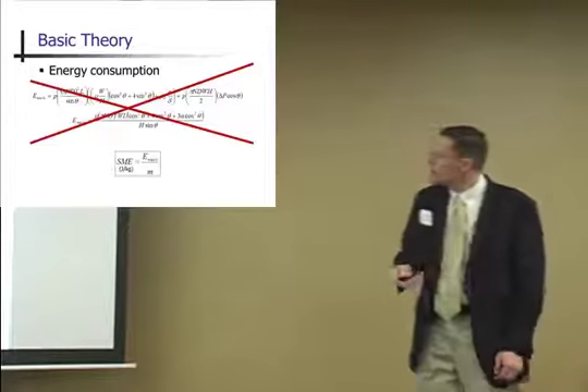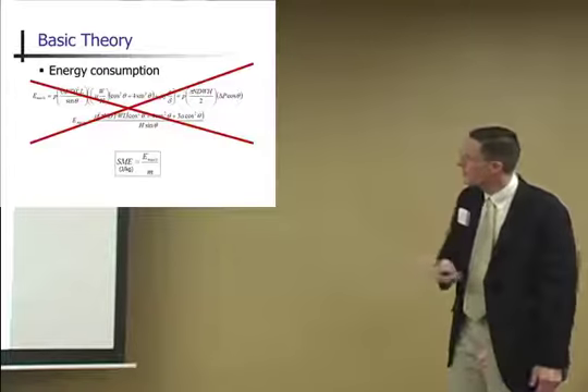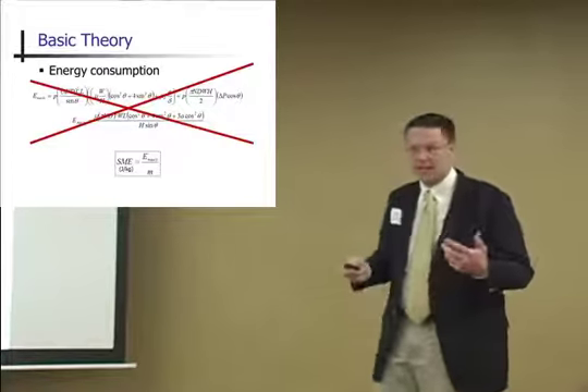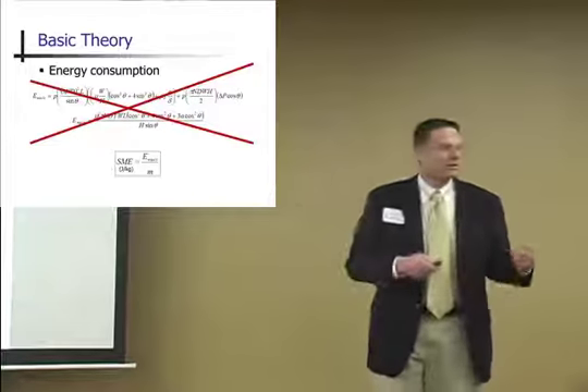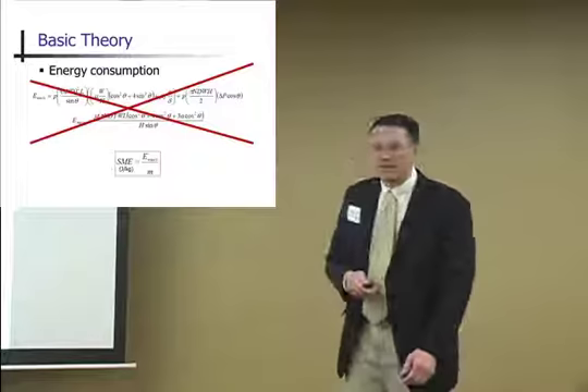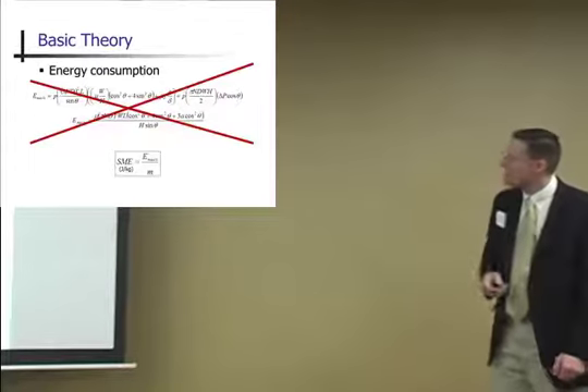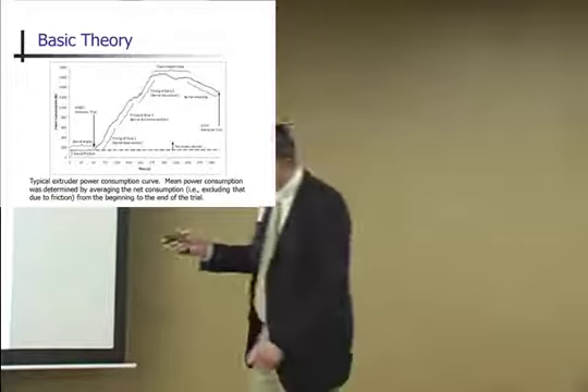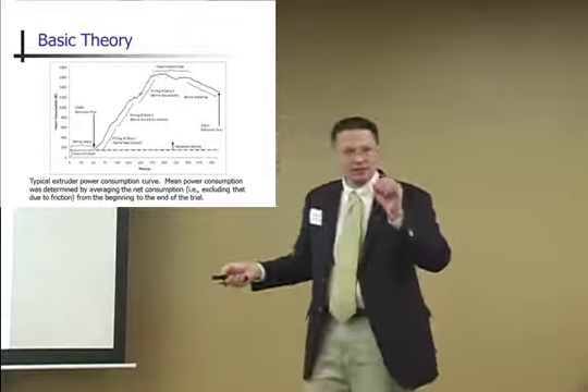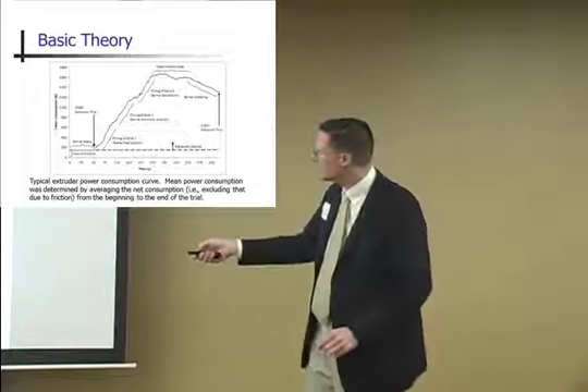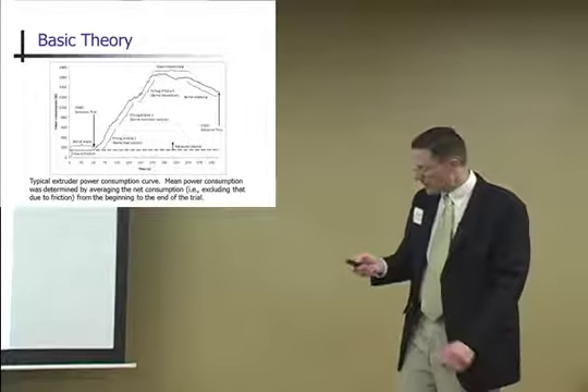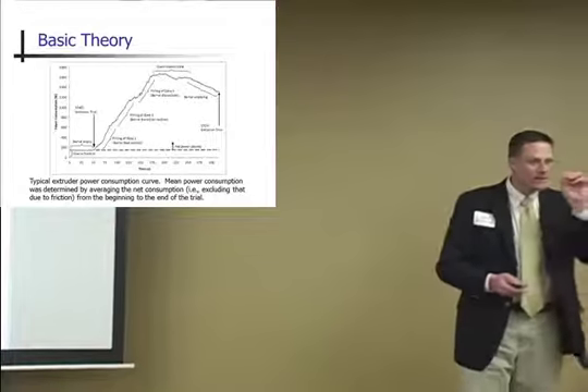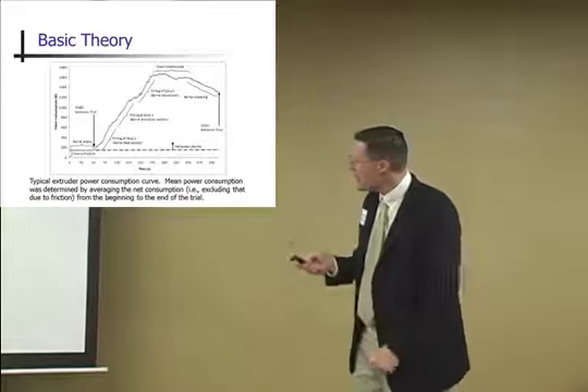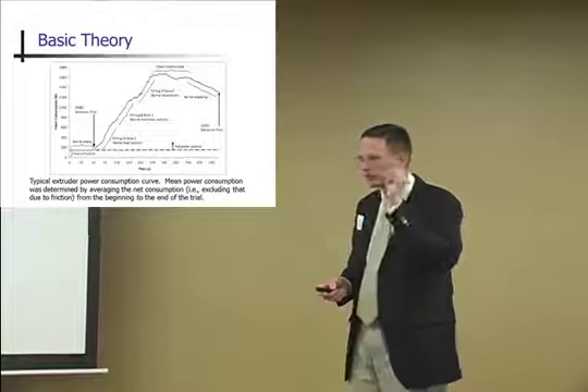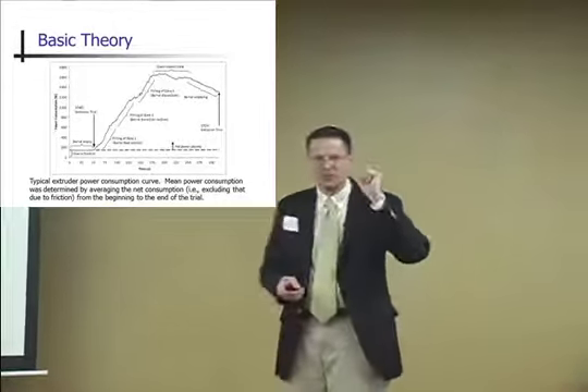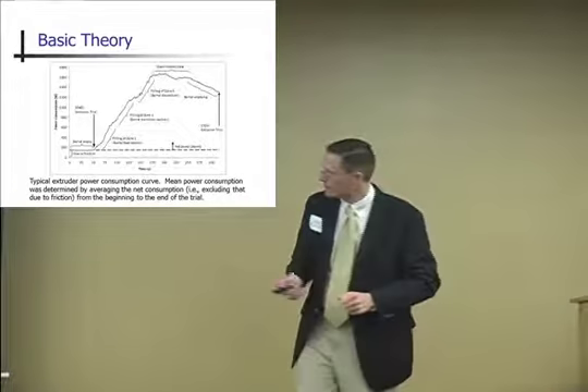So if we want to quantify energy consumption, this is how you quantify energy consumption. It depends on your geometry, your speed, your temperature, your material characteristics. You know what? I don't want to do that. You theoretically can measure the heat that you add, the electricity that's added to your heaters. You can measure the steam flow rate. But by and large, what really is used, if you have a power meter that you can plug into your extruder and measure how much energy that extruder is consuming, that's the way to do it.